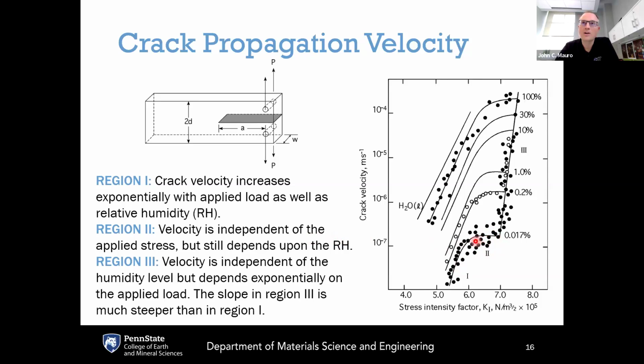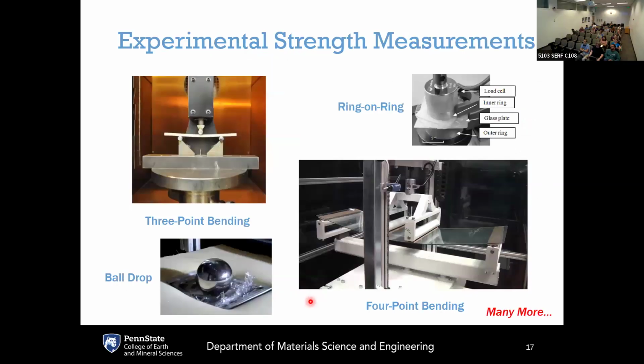This is where the crack has become long enough that the kinetics are governed by how long it takes to transport the water molecules from the outside environment to the crack tip and then ultimately react there. And then once the crack is long enough, we get to region 3, where there's a very sharp increase in the crack velocity with stress intensity factor. At this point, the stress intensity factor is high enough that it doesn't need water molecules anymore to grow the crack. So the velocity is independent of the humidity level, but still depends exponentially on the applied load. At that point, you generally have complete failure of the material.